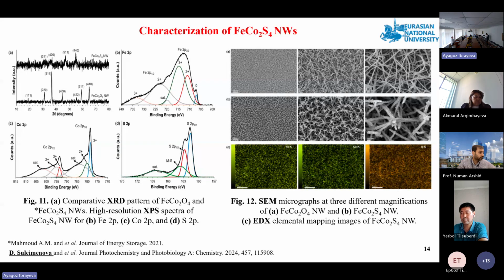Thank you for your question. All my ternary sulfides, zinc cobalt sulfide and iron cobalt sulfide, then the ternary composite, are all lower cost than platinum, because these elements are abundant and transition metal chalcogenides exhibit good electrocatalytic activity. They are much cheaper than platinum. I can show you how I calculated.